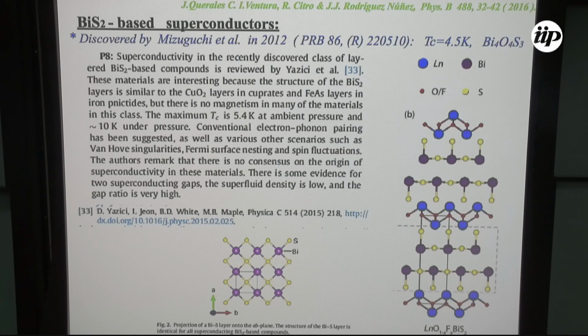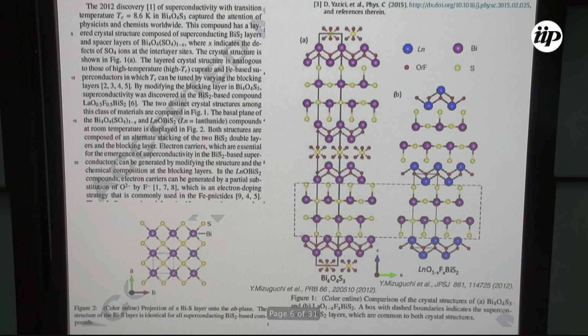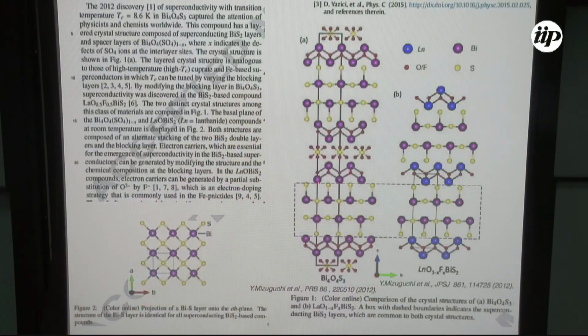And then very quickly, let me go to the next slide. In the same year, Mizuguchi also found this, the first compound. Here you will see these are the planes which have this bismuth, the violet things, and the two sulfurs connecting each bismuth. And these bismuths form like a square lattice on planes. And these planes are intercalated between blocking layers of other atoms.